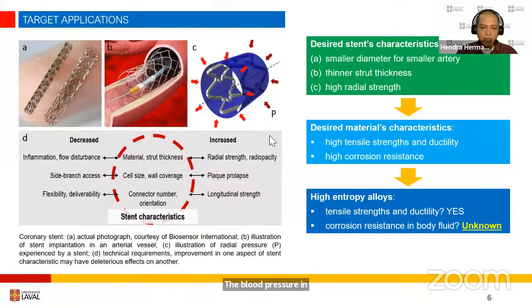And what are the ideal characteristics of stents? The material should be biocompatible. It should not induce inflammation. Then after inflammation, there will be blood clotting that disturbs the blood flow, and then re-induces the coronary artery blockage. And the strut thickness, okay, this is the strut. It's actually a tube, but a mesh tube. So the strut thickness ideally should be as thin as possible, but it should also give radial strength.